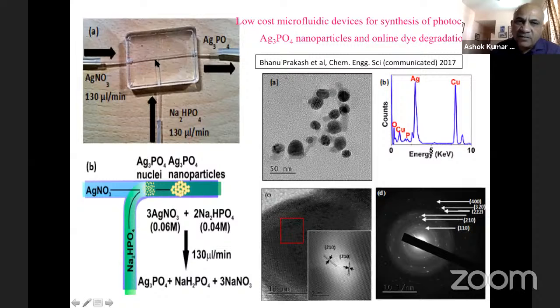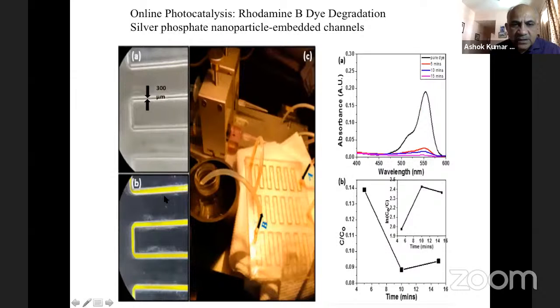We can make channels very fine or thick depending on the way you are doing the lithography. This is a very cheap method, the way we have done. We have made nanoparticles of silver phosphate and also embedded them within the channel. The silver phosphate is a visible light photocatalyst. And once they are embedded in these channels, you see the yellow color.